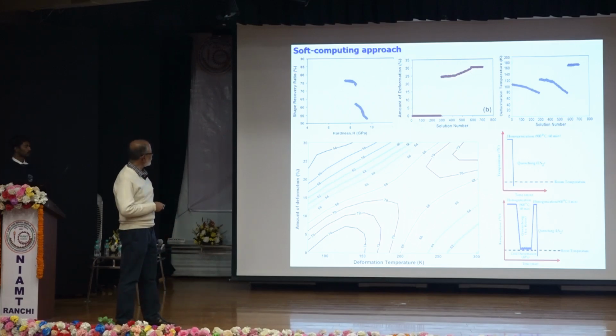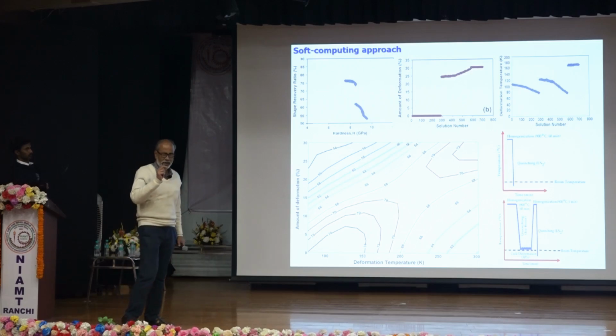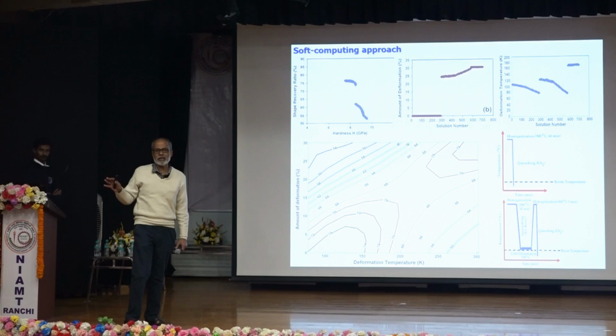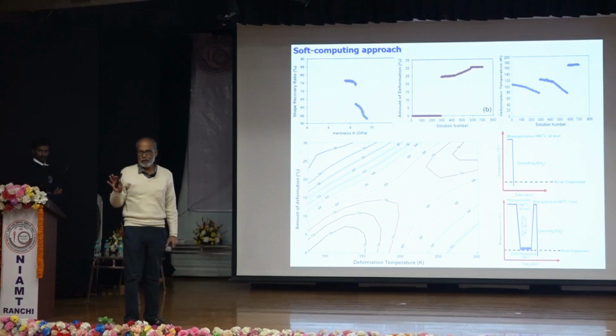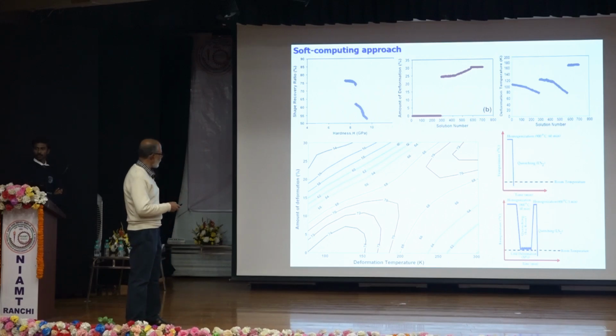And when we find the Pareto front, we find there is a scope of trade-off. I mean, there is a change in shape recovery with hardness, right? And each of these points we call an optimal solution point. Each point is associated with a set of input and output, right? So we increase the solution number in terms of hardness. This you may consider as a hardness axis.